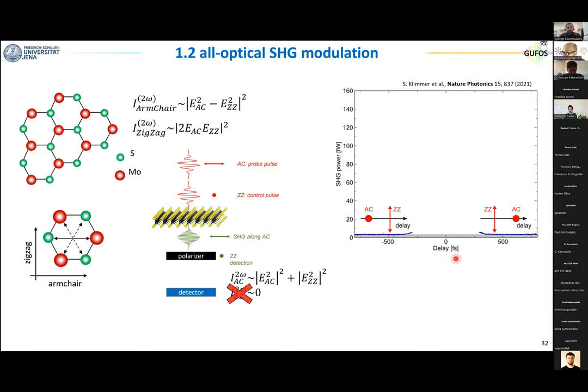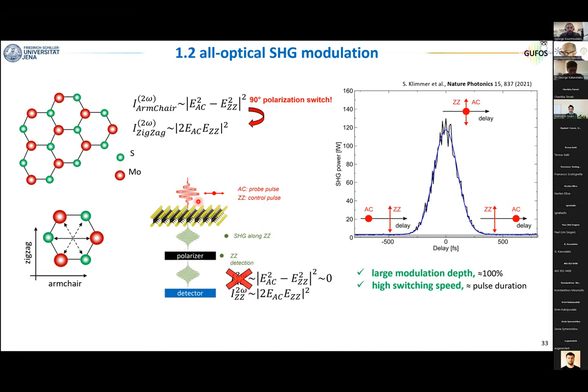So now the idea is the following. We take two replicas of the same pulse and we align them orthogonally polarized with respect to each other, one along the zigzag, one along the armchair direction. Now, we generate second harmonic, we place a polarizer in front of the detector, and what will happen is that if the two pulses are far away from each other, as you see in this graph, the delay is larger than the pulse duration, then nothing will go through the polarizer, so the signal is identically zero. And now you change the delay, the two pulses overlap, you rotate by 90 degrees the polarization of your signal, everything is transmitted through the polarizer, and you have a maximum in the second harmonic.